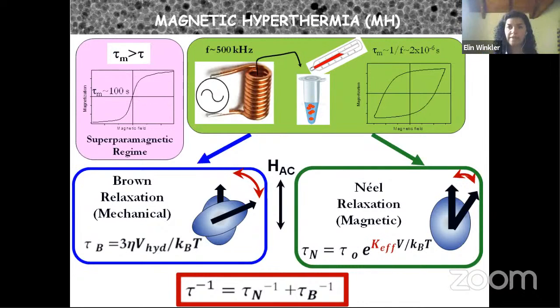We have to understand that to improve the material. Well, there are two main relaxation mechanisms. One of them is the Brown relaxation mechanism, which refers to when you apply a magnetic field, all the nanoparticles rotate in order to align the magnetic moment to the applied magnetic field, which means the magnetic moment is like attached to the magnetic nanoparticles. As the magnetic nanoparticles move in the medium, this relaxation time will depend on the viscosity of the medium.